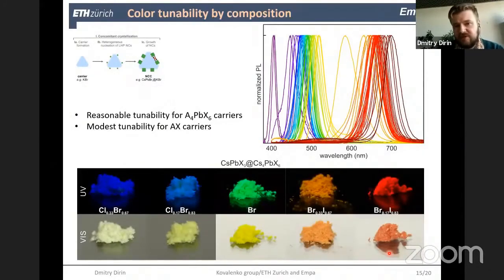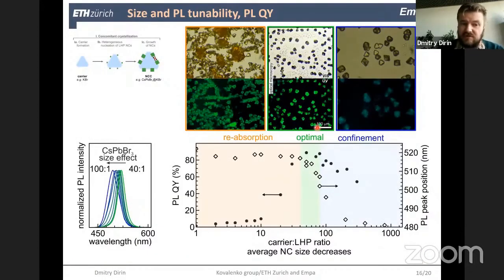I will go very quickly now through those results. We still can tune, as usual, the PL peak position by tuning the composition of those materials. We can also tune it by the size of the nanoparticles. But what is more important is that we have an optimal range of the ratio of cesium lead bromide to the carrier, the geometry between cesium lead bromide and the carrier. And in this range, we can make nanoparticles which exhibit very bright emission, around 80% in the case of cesium lead bromide.